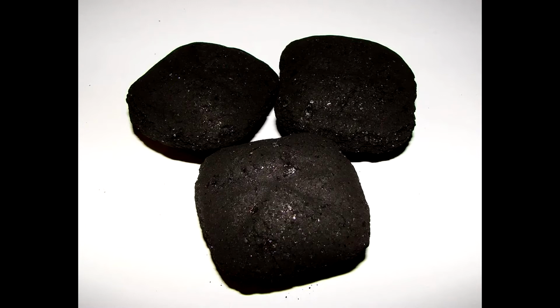It is worth getting a sense of the overall efficiency of this process. Modern charcoaling is more efficient and can often get yields, that is, the mass of the charcoal when compared to the mass of the wood, as high as 40%. But ancient and medieval charcoaling was far less efficient. Sim and Ridge, original citation, note ratios of initial mass to the final charcoal ranging from 4 to 1 to 12 to 1, or 25% to 8.3% efficiency, with 7 to 1 being a typical average, 14%.